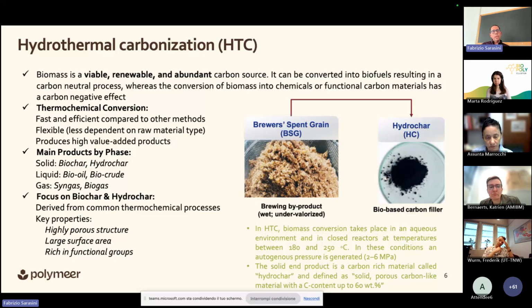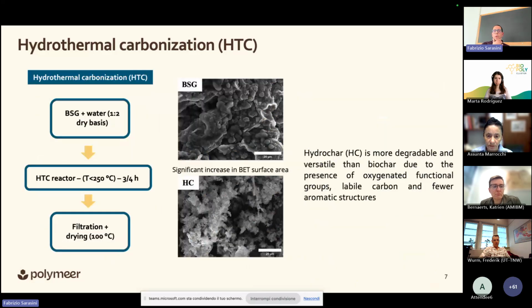And in the end, what we get is a solid material called hydrochar, which can contain a carbon content as high as 60% by weight. This material shows quite a high specific surface area, and it is very rich in functional groups. Here you can see how the morphology of the wet biomass is converted to hydrochar, and in particular we detected a significant increase in the specific surface area.